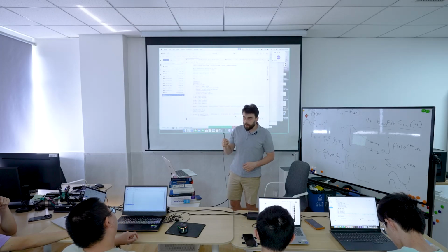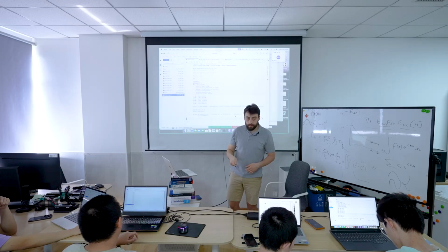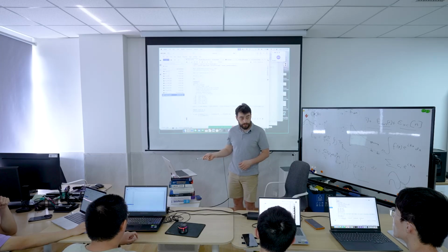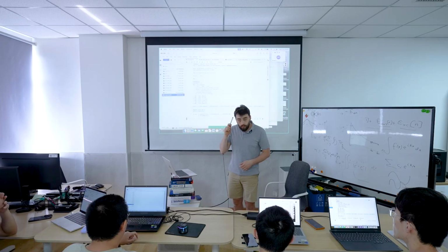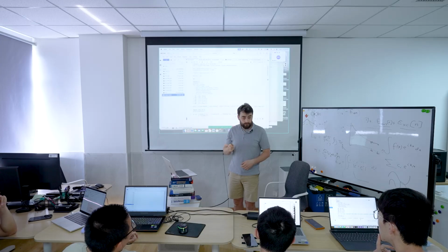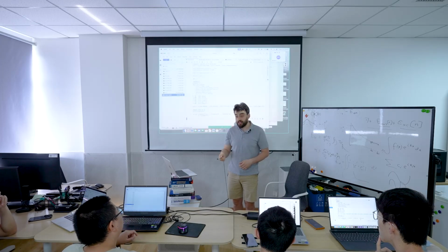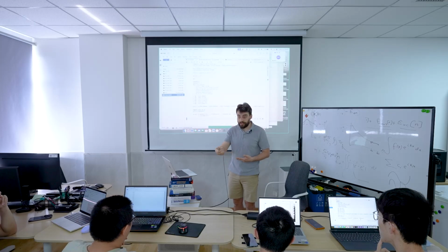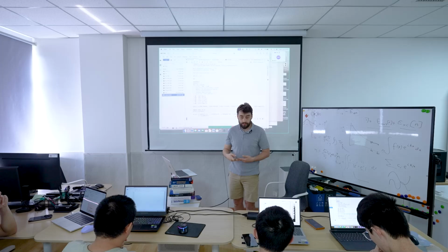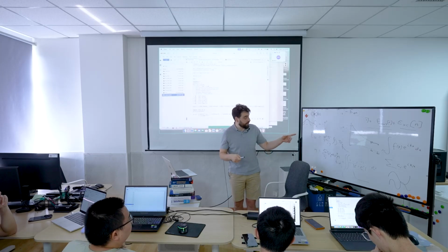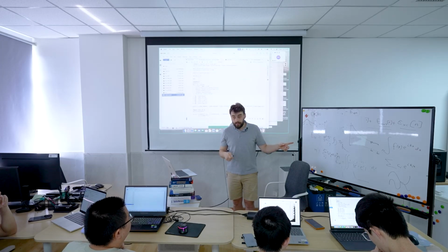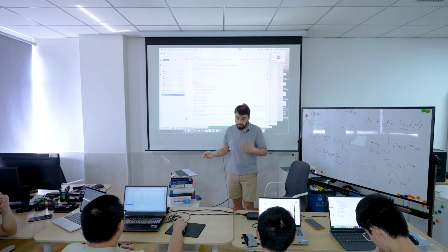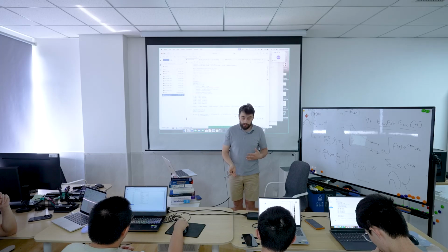But we need to know why this one is higher than this one. Can you do a calculation on both of these systems and look at the difference? Well, it's pointless and worthless for you to do a calculation with an accuracy of less than 10 to the minus 1, because then it's not going to predict the experimental result. So this is how we decide when it's converged. We think, what would be good enough in order to predict something from experiment? 10 to the minus 2 would be good. We'll stop at 10 to the minus 2.